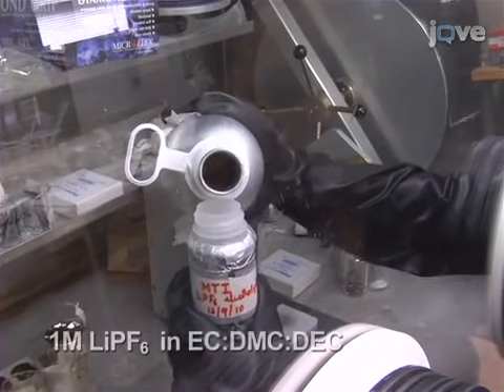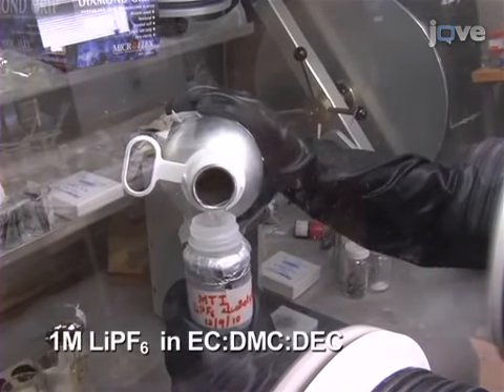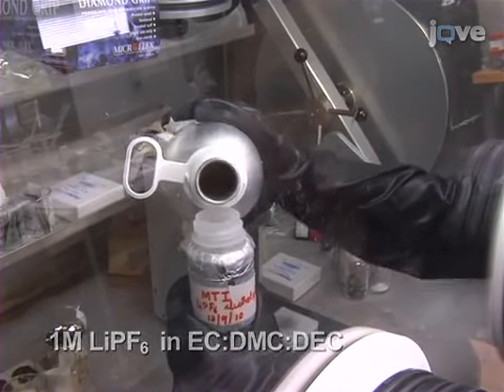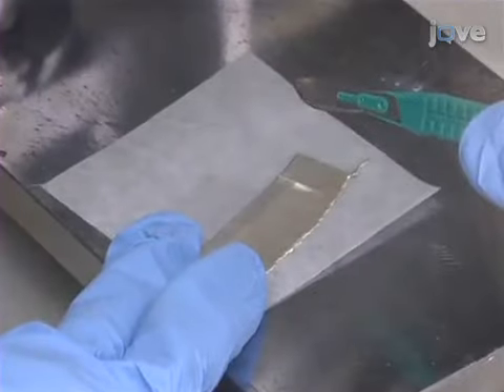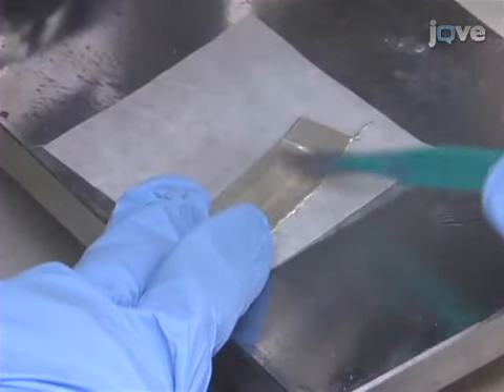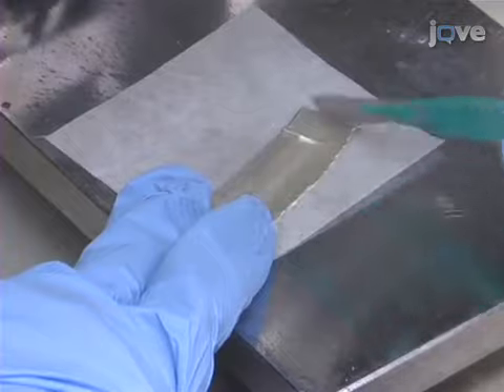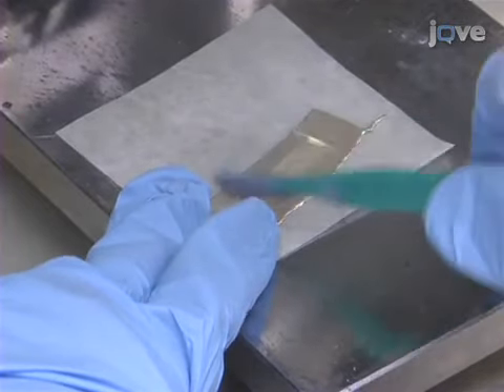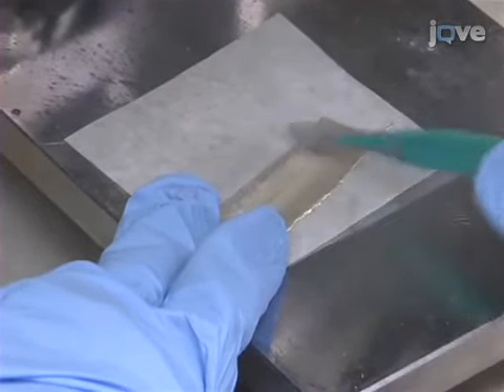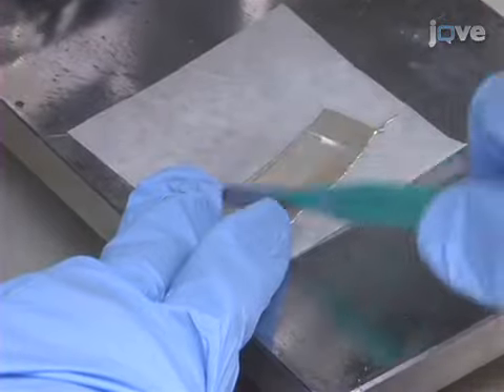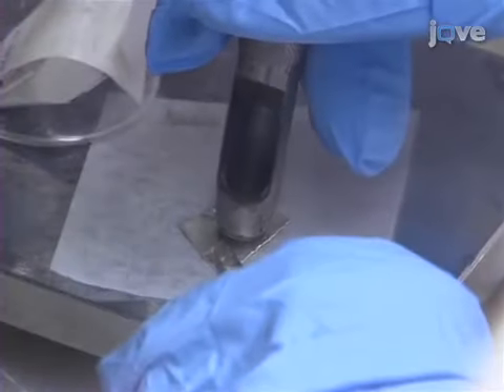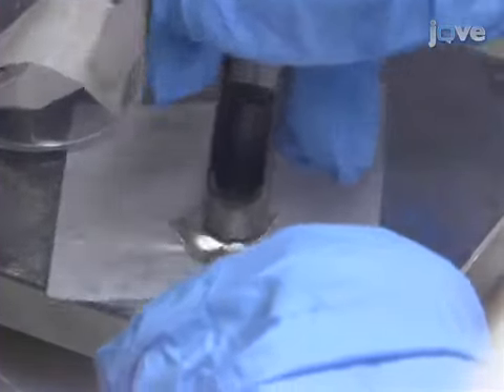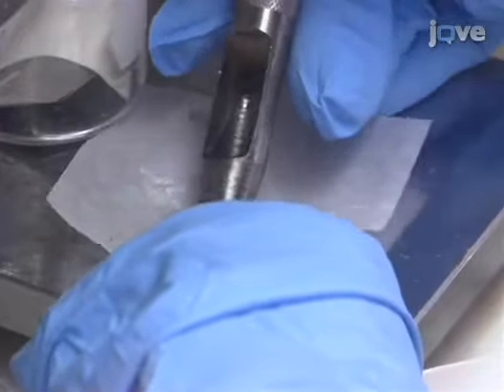As the electrolyte is photosensitive, store it in a Nalgene bottle wrapped in aluminum foil. Inside an argon glove box, use a nylon brush or stainless steel scalpel to clean the surface of the lithium foil until a shiny, silvery surface appears. Then, punch 12.7 mm discs of the lithium foil.